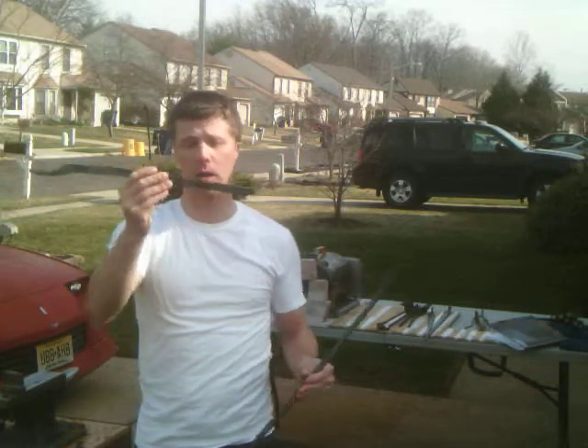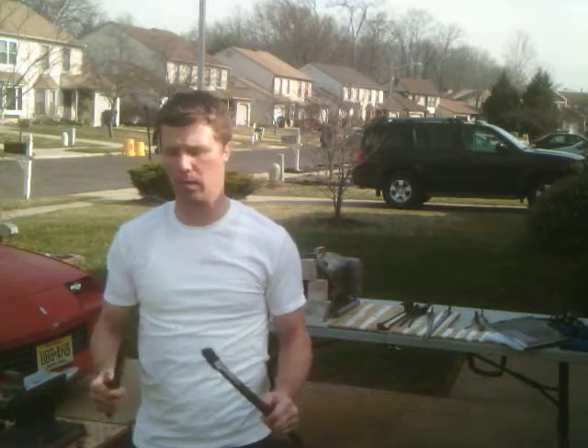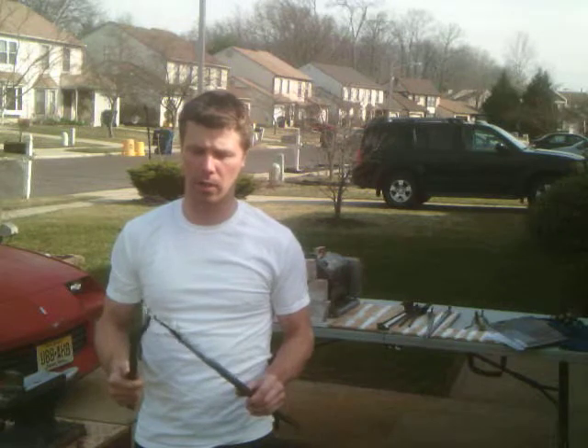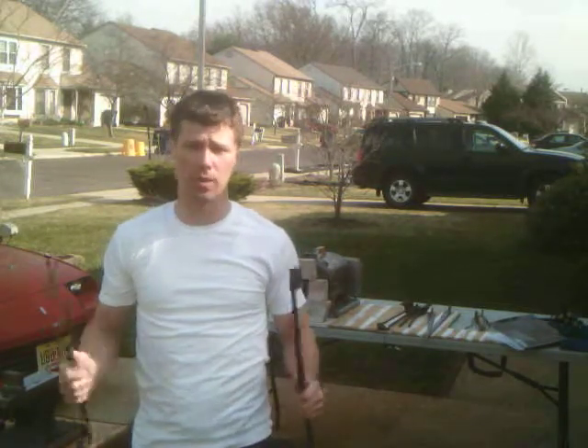I was really good at drawing it out in a bar — it comes out in a square bar, I can draw it out, make it longer, make it go square. That's great and everything. But I wasn't really keeping it hot enough, and I was doing things to the steel that you shouldn't do at certain temperatures — like when it started to cool, trying to bend it and whatnot. That creates stress fractures. You don't want to do that. So when you're working with steel, you want to keep it hot. You want it in the red. After you've shaped it a bit and you see that it's starting to lose that color, you've got to pop it back in the forge to let it heat back up.